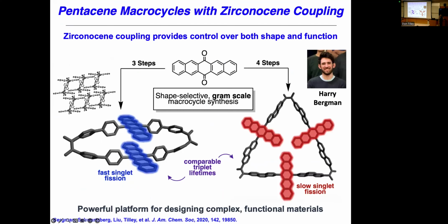But one of the things that we think is interesting in terms of having a high-yielding macrocyclization that we can use is to orient chromophores in a macrocycle in different ways to interrogate their interactions. So we did that in the context of singlet fission, where we were able to pretty easily install pentacenes into macrocycles that were either dimeric, and that's because of the biphenyl linkers that can bend a little bit, or trimeric, and that's because these units are locked into phenanthrene type units like this. And so we were able to measure the rates of singlet fission in those cases.